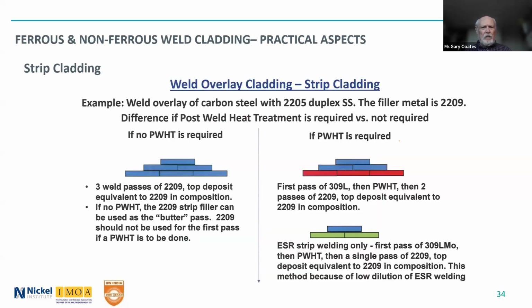Just taking one example here of weld overlay of carbon steel with the 2205 duplex stainless steel using the standard filler metal 2209. And this compares if the post-weld heat treatment is required versus not required. So if it's not required, you do 3 weld passes of 2209 and you get the 2209 composition on that third pass. 2209 can be used as the butter pass, that first layer, for that case,